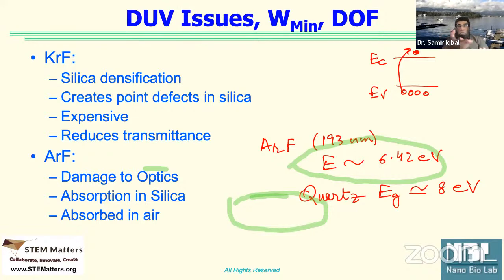That means it would start messing up their atomic structure. So that's one of the biggest problems written here, what we call silica densification. When glass becomes dense, it stops transmitting the light through. When the light can't go through,